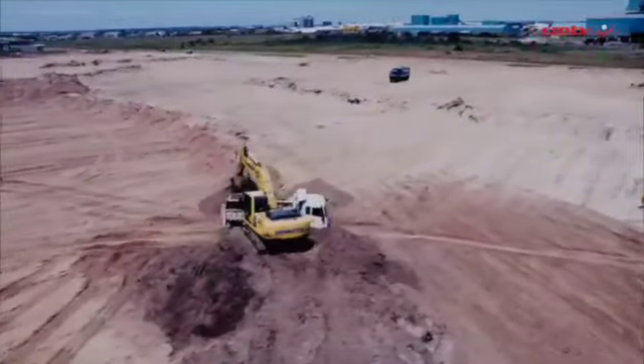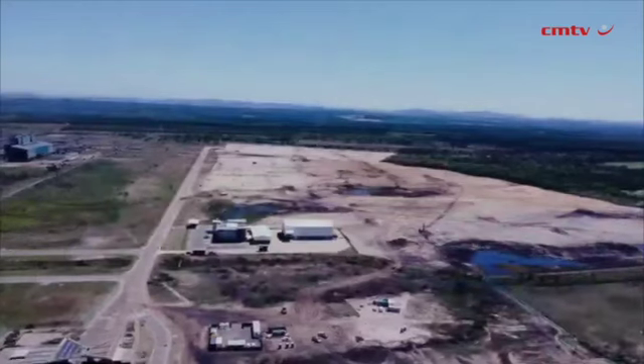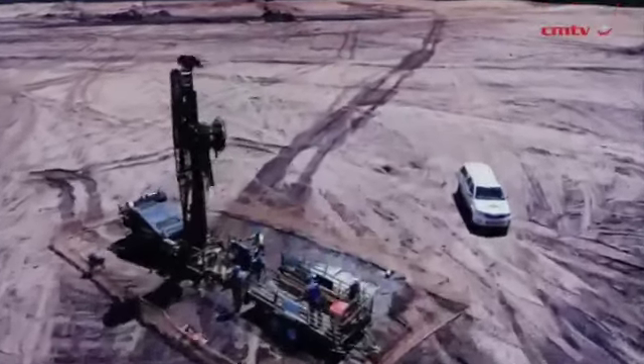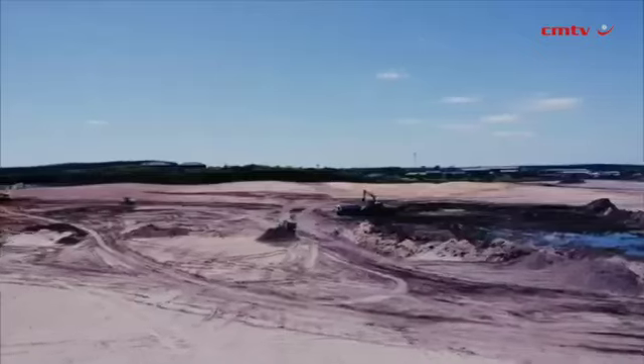In China, the plants built by ECC, our partner, all operate on a full circular economy basis. The iron sulfate is taken to produce lithium iron phosphate. You take the iron sulfate, you already have the sulfuric acid, you bring in phosphate rock, you produce high purity phosphoric acid, and you react it with the iron sulfate to get iron phosphate. That's your first stage battery material, used as a cathode material in electric vehicles, batteries or storage systems. Then you react that with either lithium carbonate, lithium hydroxide or lithium oxide, with just calcination, and that gives you lithium iron phosphate, which is the dominant battery material according to all the reports. If you look at the Teslas, the BYDs, most of their vehicle batteries are built using lithium iron phosphate.